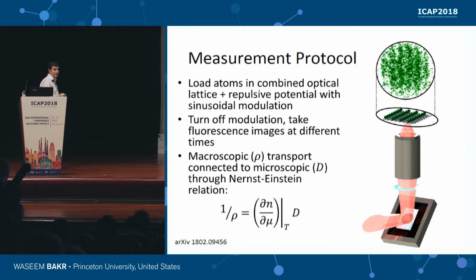Okay, so the idea behind the experiment is we load the system adiabatically, so we have the lattice and this long wavelength modulation, and now we suddenly switch off just the long wavelength modulation. But we let the system now equilibrate in this lattice. So the fermions start to diffuse, and eventually we lose the contrast of this modulation. From this diffusion, we can extract a diffusion constant, which is a microscopic quantity characterizing the transport. And we can link this to a macroscopic quantity, the resistivity, using the Nernst-Einstein relationship.